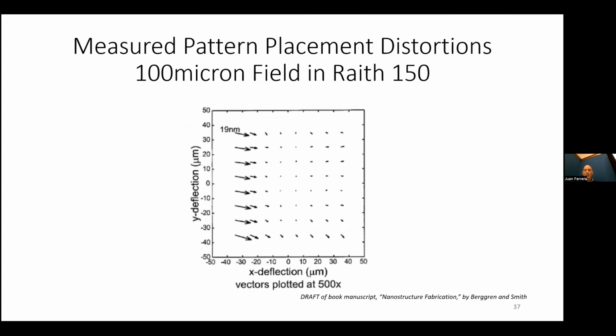So this was the work of a PhD student back in the early 90s who very, very carefully calibrated fields and did a nice plot here of what the 100 micron field in a Raith 150 looked like. It's showing you vectors that are magnified 500 times with respect to the XY axis, showing where the displacement is.